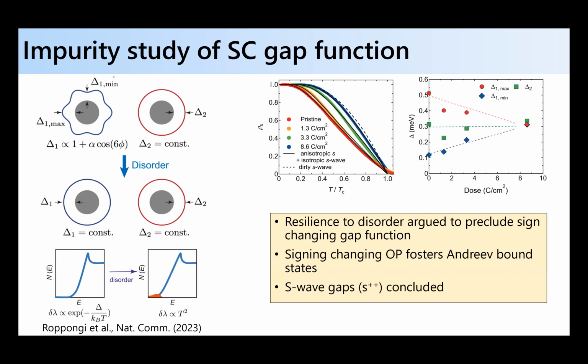This is some beautiful work by Roppongi et al. and Shibauchi here, on penetration depth using irradiation damage. In the sort of disorder-free limit, they basically fit with one anisotropic gap, but fully gapped, and one isotropic gap. And so from this study, because of the resilience to disorder, you could suggest that maybe you could exclude sign-changing gap functions, so maybe an S++ is the most likely.